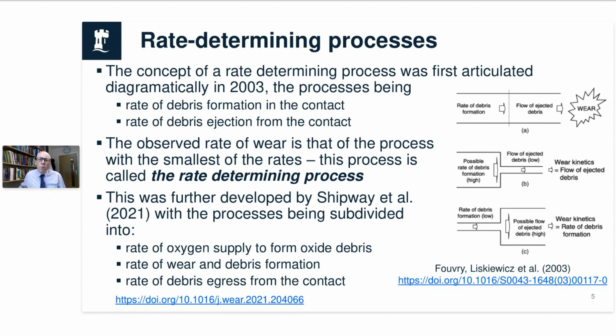In the work that we then further developed, which was in 2021, we talked about that rate of debris formation. We broke that down into 2 stages. We said there's the rate of oxygen supply. So to get this debris to form, it's an oxide debris, there's the rate of the oxygen supply. There's the rate of wear and debris formation itself, what we might call the Archard term within the system. Archard, remember, Archard's work was all about sliding wear. So the idea of applying this to fretting is somewhat of a stretch anyway. So I don't want to sully Archard's name. Archard's work is obviously foundational to our understanding within this kind of area. But Archard was primarily talking about sliding. We sometimes misappropriately use Archard within the area of fretting.